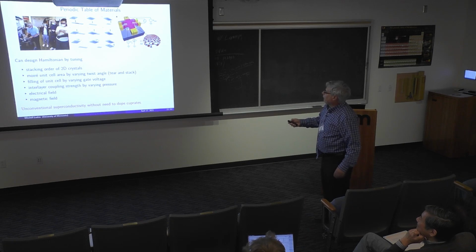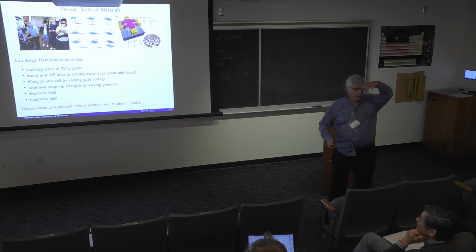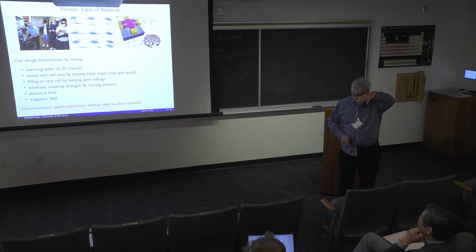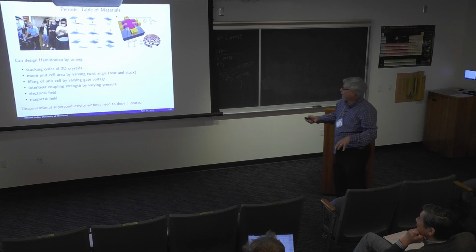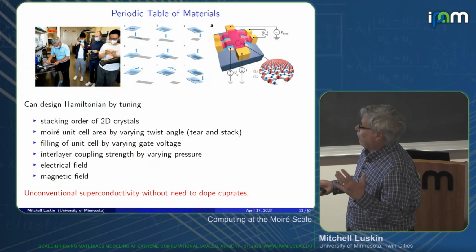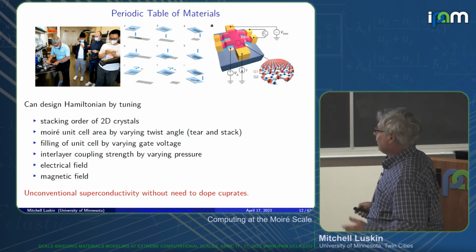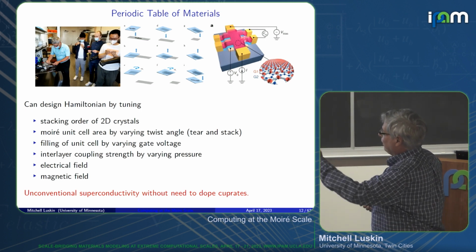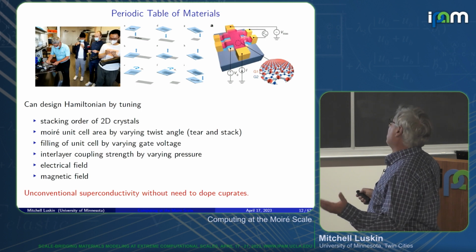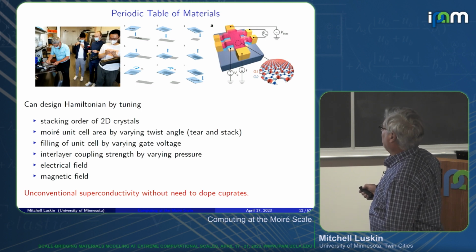You make one layer of graphene, and you bring this TMD down, and then you pull up and you tear, and then there's literally a little machine that just turns it around a little bit. It's very mechanical. And then you put it down again. This is a tri-layer system we did. So you can see all these things. It's not some big fancy accelerator you have to use. This is all just sitting there, little stuff. And then this is how you measure all this transport.